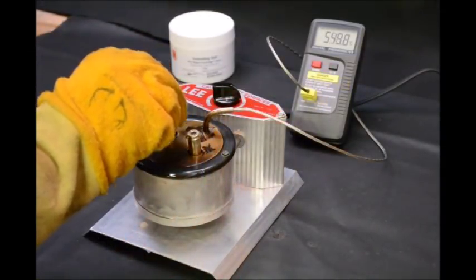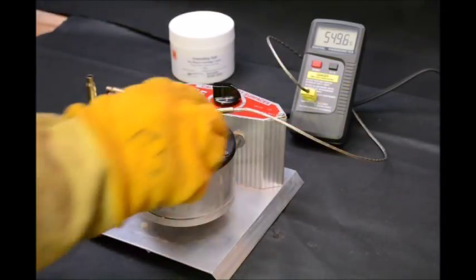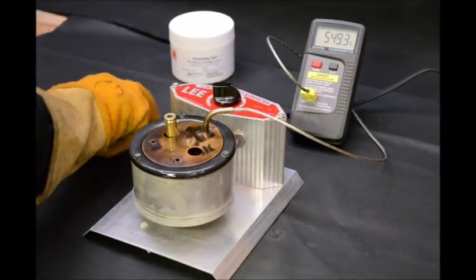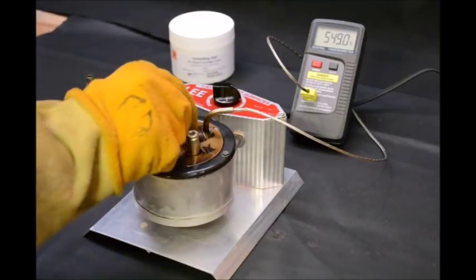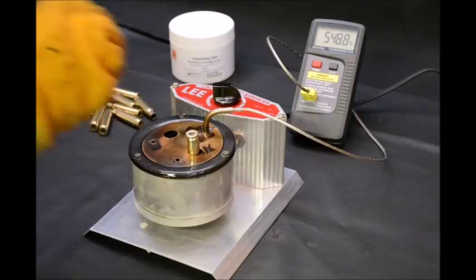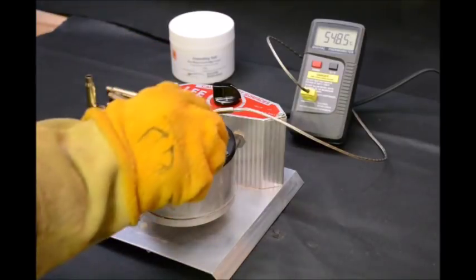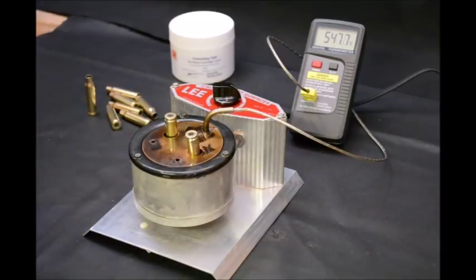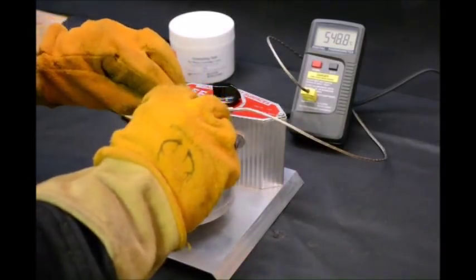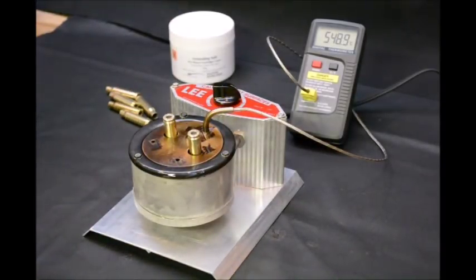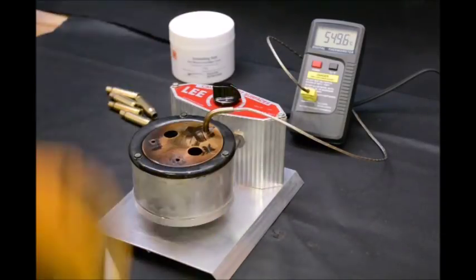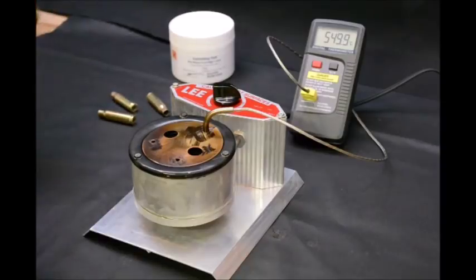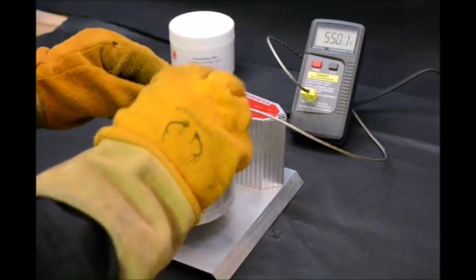Timing can be established by using a timer or metronome, or simply by establishing a consistent rhythm. The salt bath method is very error tolerant, meaning that modest differences in exposure time will have very little impact on the end result. Cases immersed for 4 seconds or 7 seconds will both be adequately annealed, though the longer time will result in heating a little further down the case. So long as precautions are taken to ensure the case head is not affected by heat, this does not pose a problem.